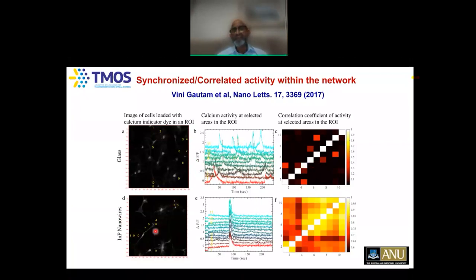So you can see that in the case when she's grown these neurons on glass substrates, the fluorescence intensity changes as a function of time, essentially the calcium concentration determines the change in fluorescence intensity. You can see that they're all firing randomly. You see very little correlation coefficient here. But whereas the neurons grown on indium phosphide nanowires in ordered arrays, you can see that all these neurons are firing at the same time. You see excellent correlation coefficient, indicating there is some sort of synchronized and correlated activity taking place.